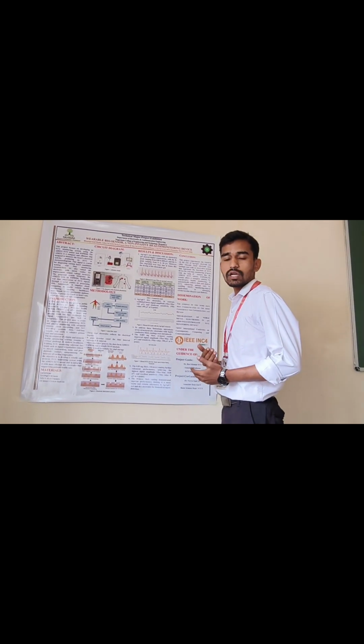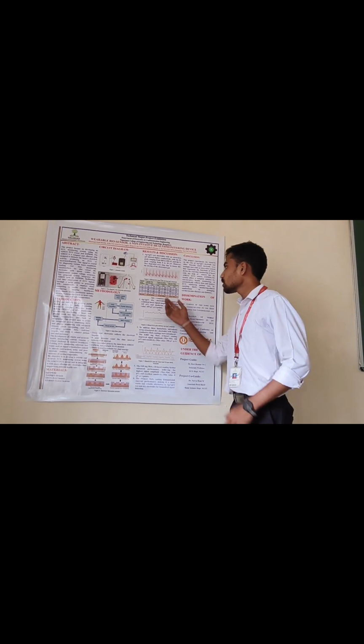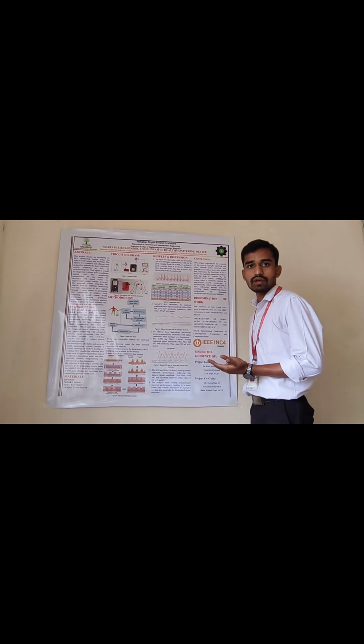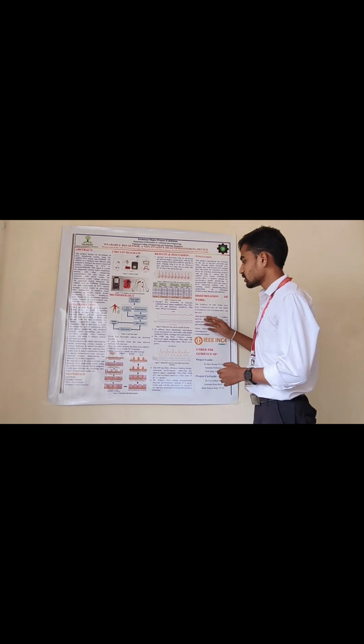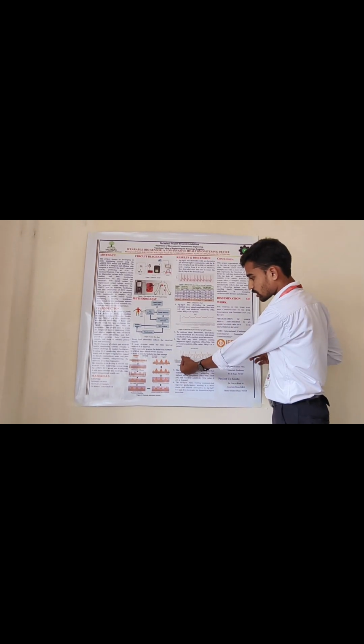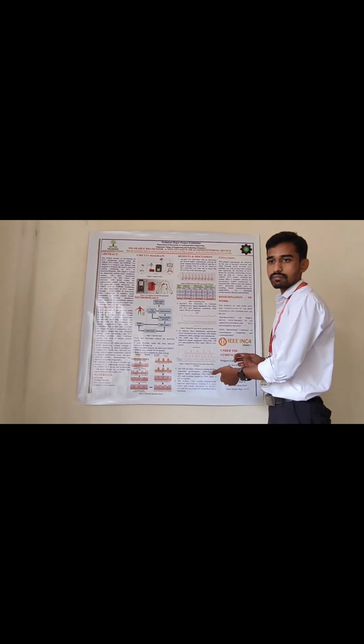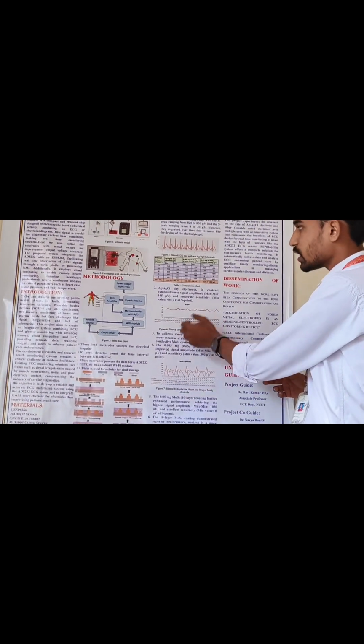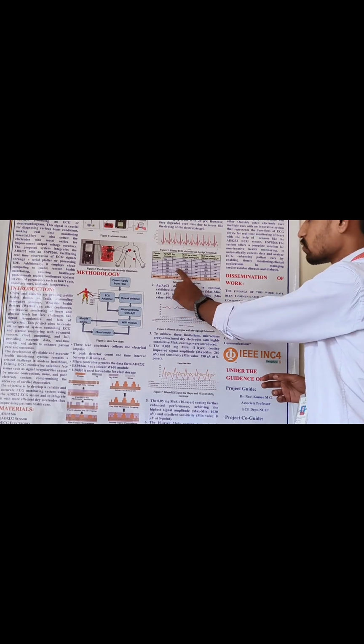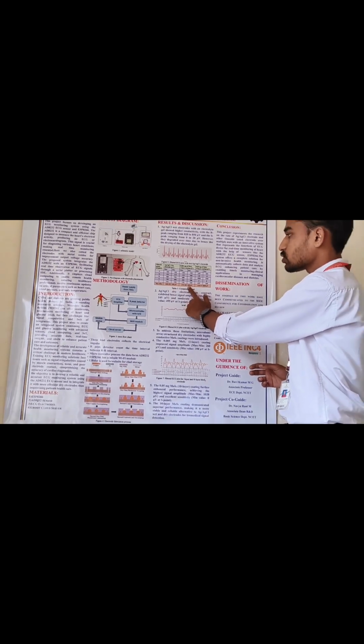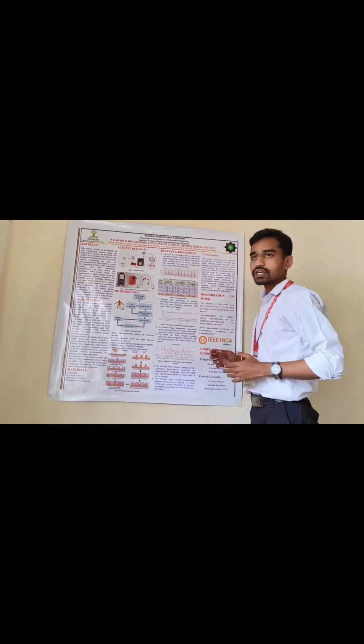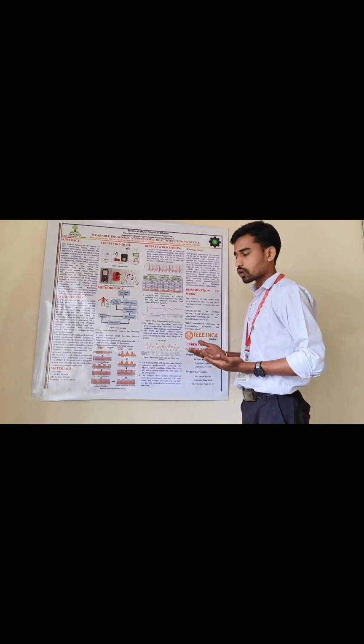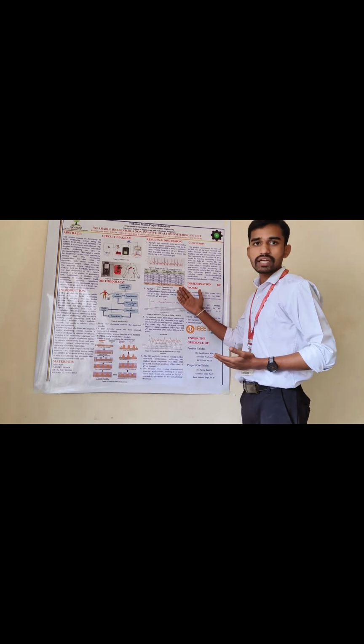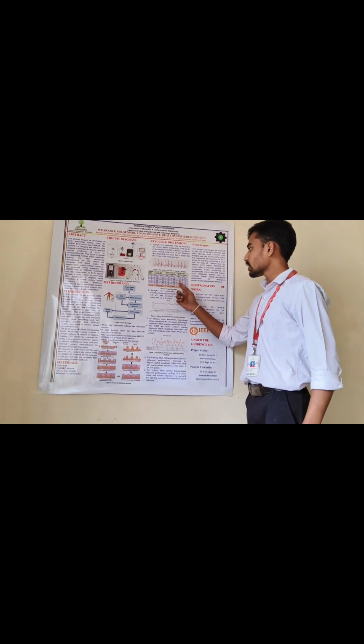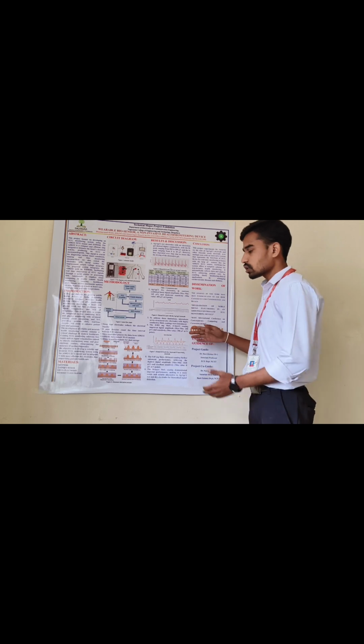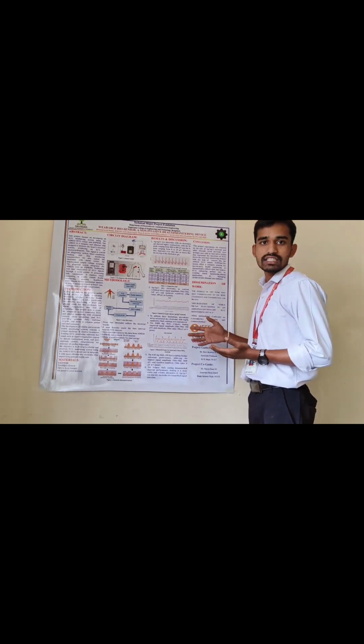When we coated a single layer of molybdenum disulfide, it accumulated about 0.005 mg of molybdenum disulfide for a single layer, and there was a distinguishable result. This yellow line is the result of the single layer molybdenum disulfide, which was pretty high compared to the AgCl dry electrode, which gave almost double the bandwidth, that is 260 microvolts of range. And when we made the same 10 layers of coating for the same electrode, it gave about 1020 microvolts of difference, with the highest peak at 1020 and the lowest S peak at 0. So the difference between the R peak and S peak was easily distinguishable through this.